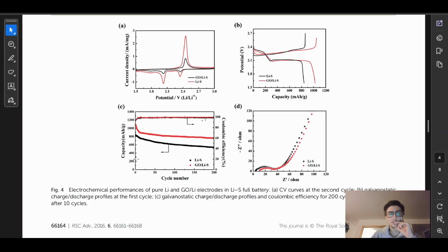So the first cycle is all the way over here, boom, and you can see the graphene oxide lithium sulfur battery is in red over here. And they have these arrows here. I'm not sure what this means. Maybe this means charge and discharge. But anyway, take a look at this. Right here, the first dot is up here, specific capacity that's high. And then after the first cycle, it goes boom, boom, boom, and it falls. And maybe here, somewhere around the 10th or the 5th cycle, it's fallen considerably, like from 1100 to maybe like 900 here. Boom, little drop. Maybe that's what they mean.